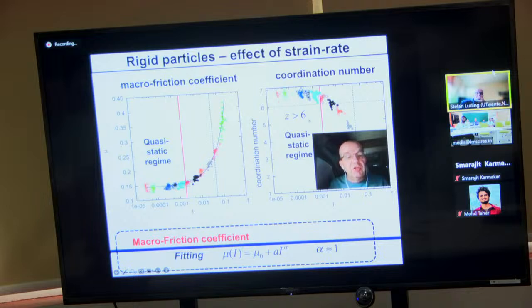Now, for the macro friction, the solid line is well fitted up to a certain extent by a linear function in I, where alpha is almost 1. So constant plus a linear function in I. Note the logarithmic axis here.